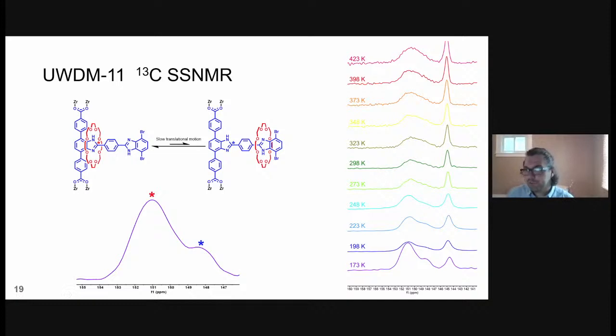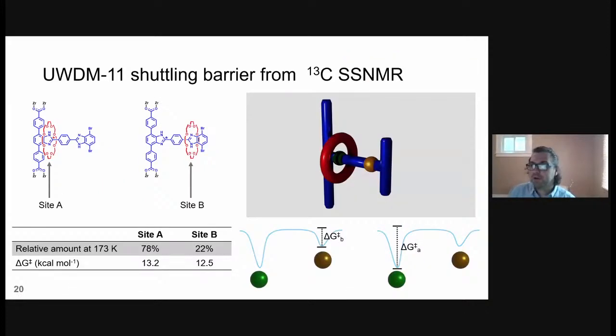And that allows us to start to estimate some approximate energy barriers for this translational motion. So at 173 Kelvin, you can see that it's approximately 78% at site A, which is this end here, and 22% at site B, which is this end here.